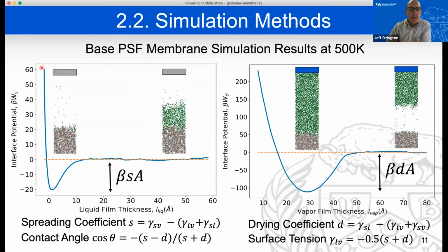So what we're showing here is the interface potential for one of the two different ways in which we implement these types of simulations. One approach is what we call the spreading approach. And in the spreading approach, we grow a thin film from the surface. So in this case, we're growing a thin film of water from the polymer membrane surface. And we've taken this particle number probability distribution, and here we've just converted it. Instead of using the particle number, we're using the thickness of the liquid water film associated with the film.